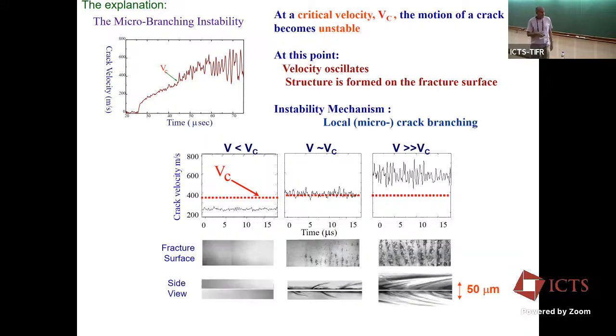So if we look now from the side, so now we're taking our experiment and we're only going to look at half of it just because I only have two hands. And we're looking now from this direction through a microscope. What we see is that at this point where we have simple cracks, there is no structure. Everything is very boring. These points here, if we look from the side, we see microscopic crack branches. So the main crack is going along this plane here, but we have these microscopic little guys that branch out and then die. So they're arrested cracks. And as we drive this crack faster and faster, they become much more dense and larger. And then we already have a lot of complexity here.